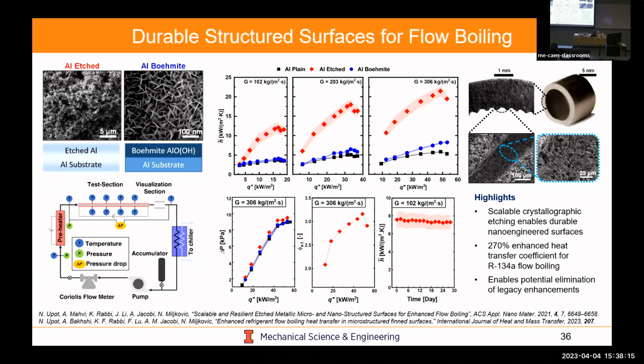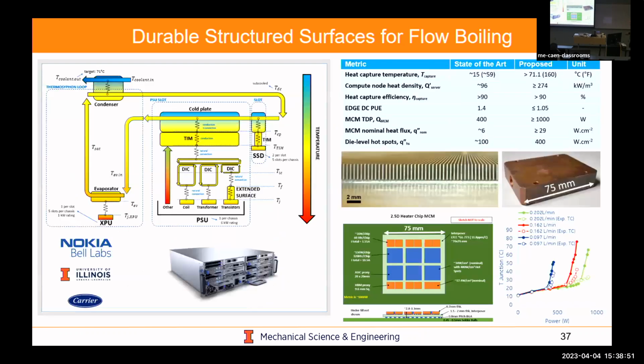Well, we've also worked with Brazeway, that company I mentioned, to look at microfin tubes. These microfins are what they currently use in the manufacturing process to enhance the heat transfer. The nice thing is by using this etch step, you can actually remove these fins and save yourself die wear and also use materials which you can't use with these microfin tubes because they're too hard. And so this is a technology which we've developed in collaboration with Brazeway. If you look at things like pressure drop, minimal changes, minimal increase, and then durability, this is again 30-day trials. We currently have trials that we want to run for multiple months to make sure this works. And so you might ask, well, where is that used, right?